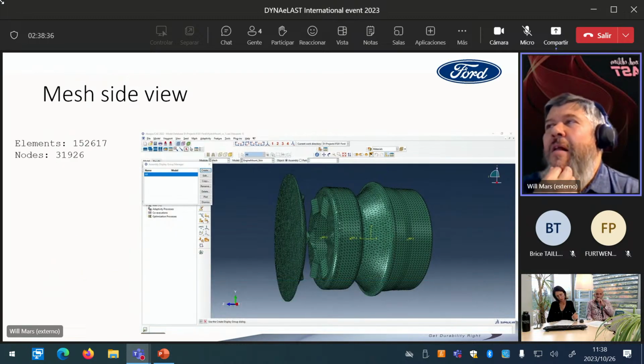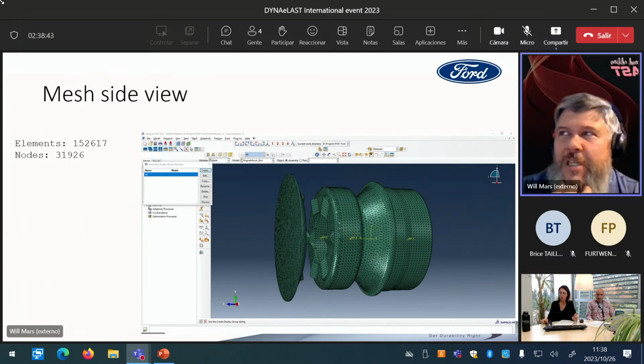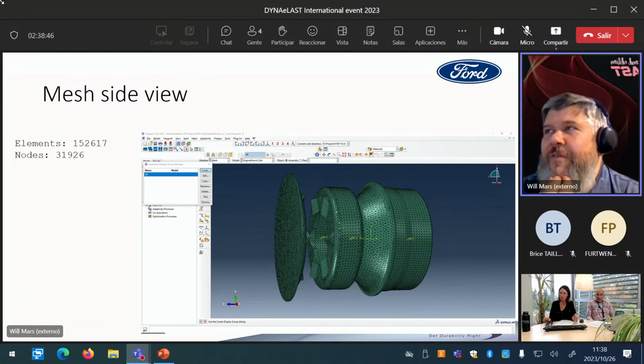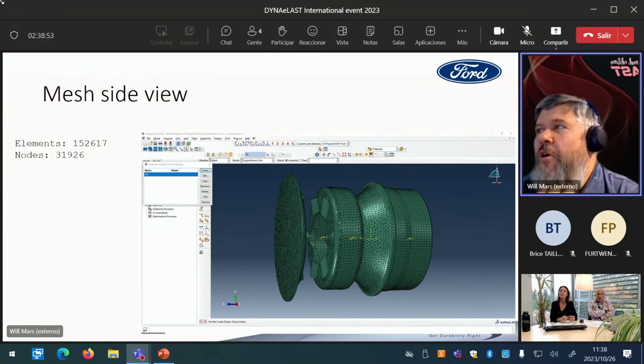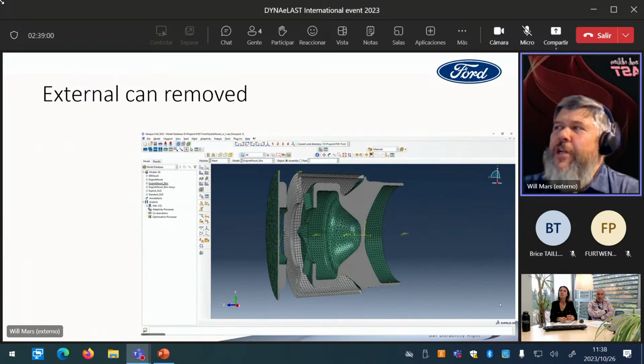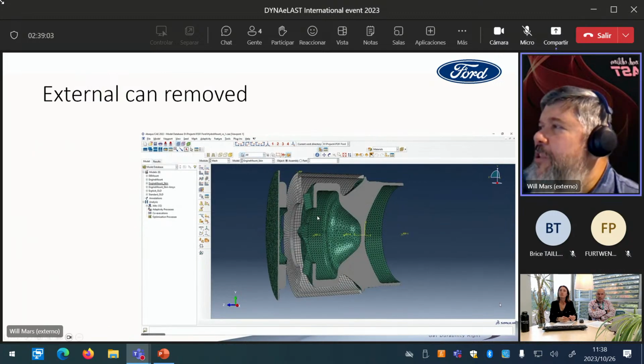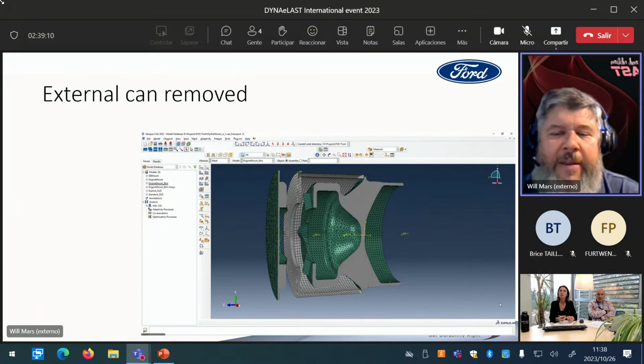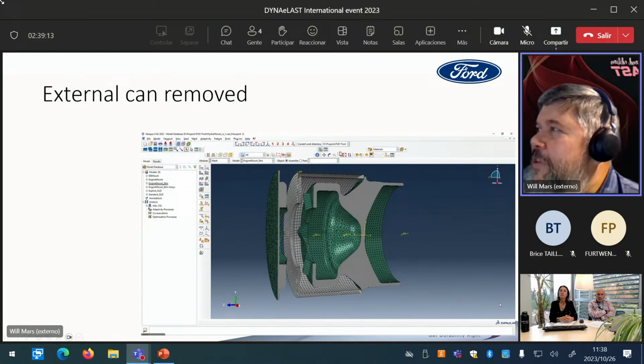The model of the mount is shown in this image. We're using hyperelastic materials. There's contact defined here. We have about 150,000 elements in the model, 30,000 nodes, just to give you a sense of the scale of the problem. Here's a cutaway view. All of the green parts are the actual rubber. This mount is sort of enclosed within a metal can or a metal cylinder that we've just modeled here with rigid shell elements. But all the green parts and the cross section that's shown in gray here, that's the rubber.